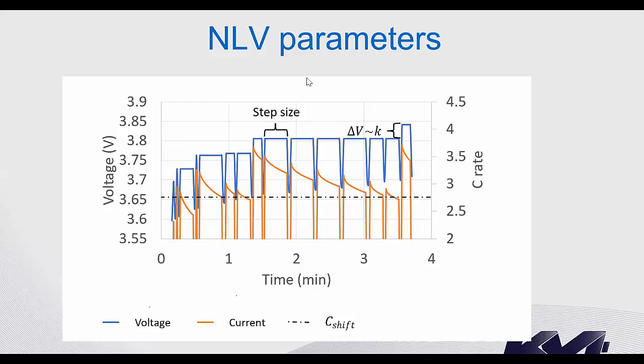So this slide shows an example to illustrate how the NLV works. Basically in NLV we have a succession of voltage plateaus like this one, and this one. In each voltage plateau, we apply a constant voltage, and we monitor the decrease in the current during the voltage plateau. And when the current reaches some value, we go to 0. The current goes to 0. We call it a rest. And that rest takes only a few seconds. And then we apply this plateau again, and so on, until the current drops below some value that we have here. When the current drops to this value, we go to the next plateau.